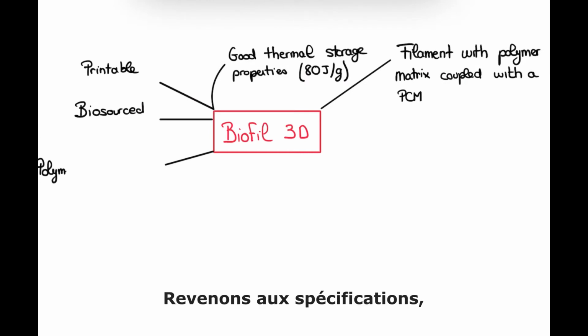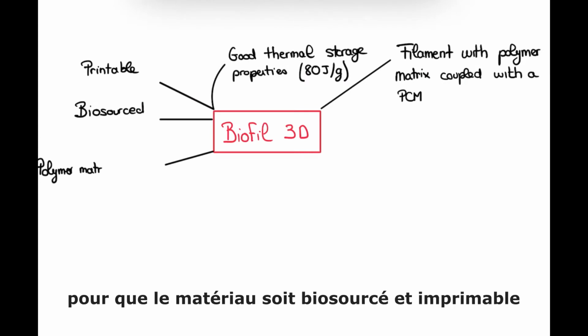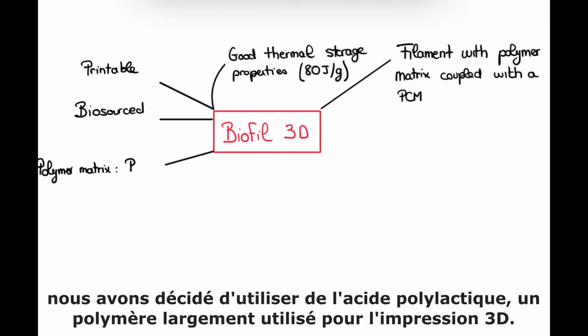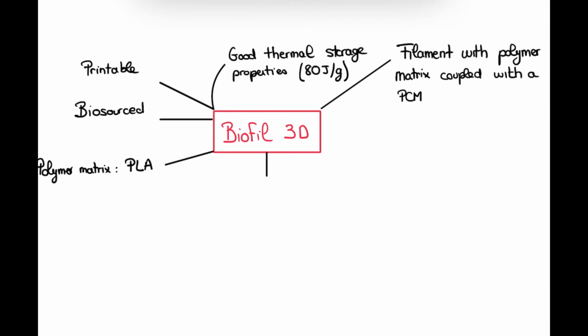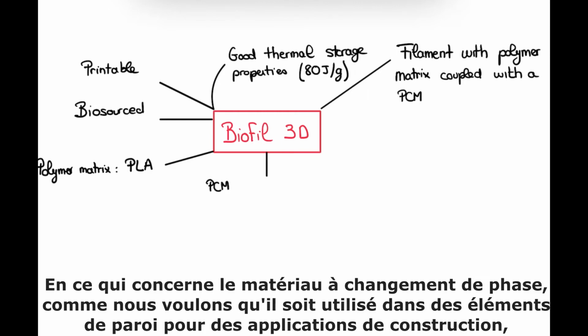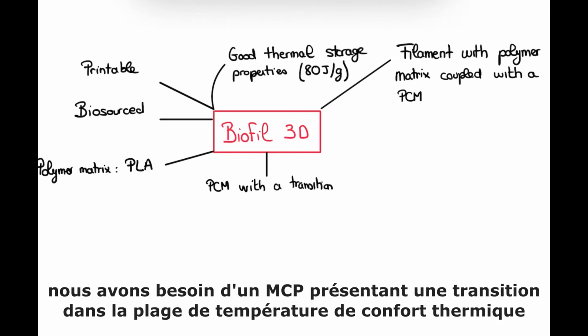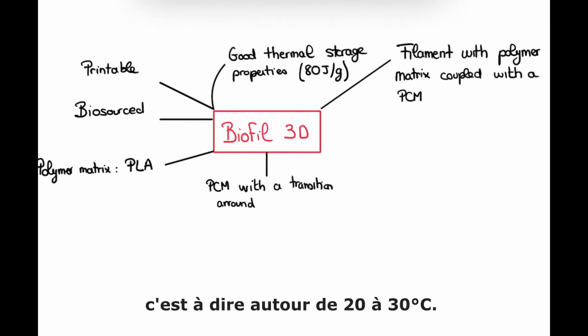Now coming back to the specification, in order for the material to be biosourced and printable, we decided to use polylactic acid, a widely used polymer for 3D printing. As for the phase change materials, because we want the filament to be used in wall elements for building application, we need the PCM to show a transition within the thermal comfort range of temperature in a building, meaning around 20 to 30 degrees Celsius.